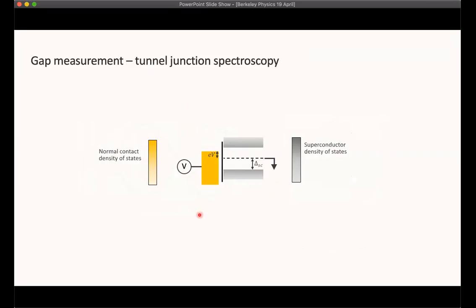Tunnel junction spectroscopy is a relatively well-known tool in the condensed matter physics toolbox. When you have a barrier between two materials, you can measure the tunneling across that barrier. And it turns out that the tunneling spectrum will be influenced by a couple things. It'll be influenced by the transparency of the barrier, but also by the density of states on either side of the barrier. So if one side of the barrier is a normal metal, a relatively boring density of states, Fermi-Dirac distribution, but for the purpose of this, we'll just say it's a relatively uniform distribution up to the Fermi level.